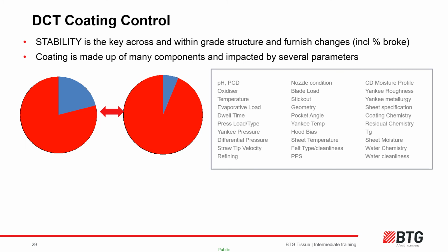So stability is really the key to a nice robust coating, which is the key to getting the most out of your blades, regardless of their metallurgy. Yes, harder blades will deal better with harder coating, but having a soft, robust but responsive coating is always the first objective for any blade material.